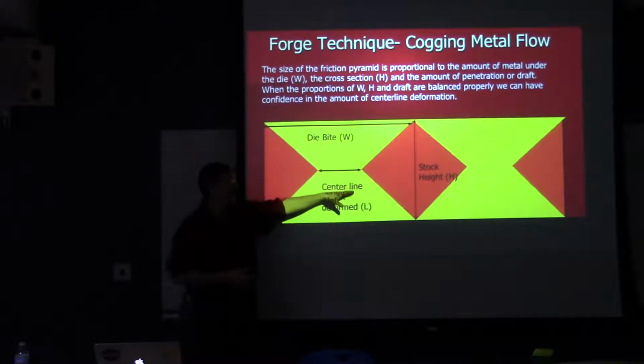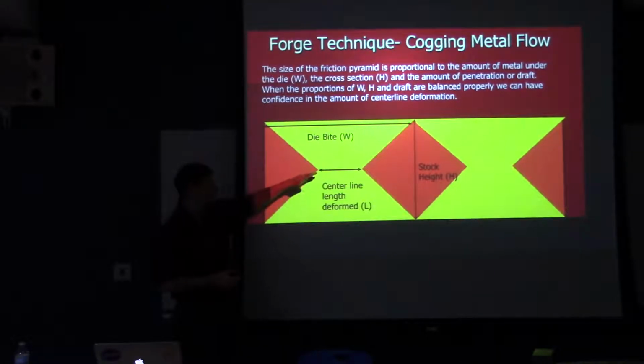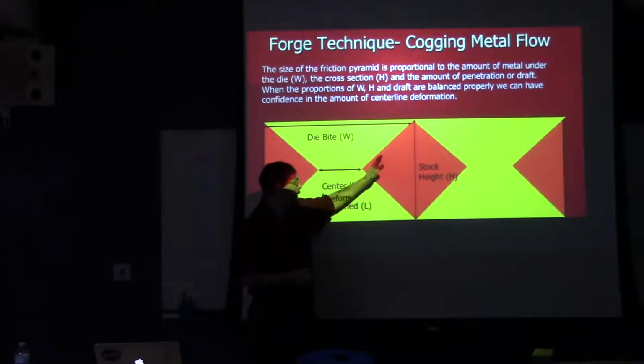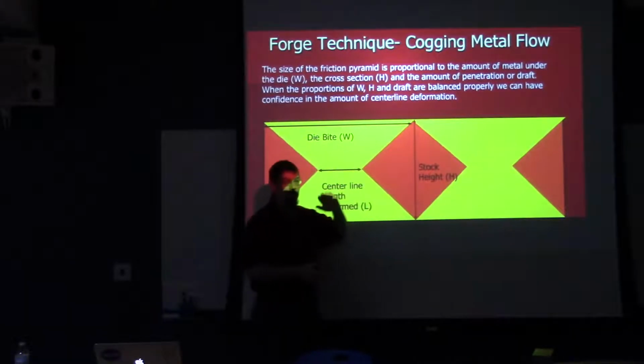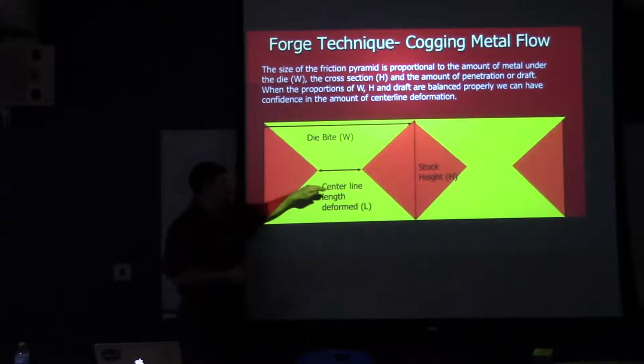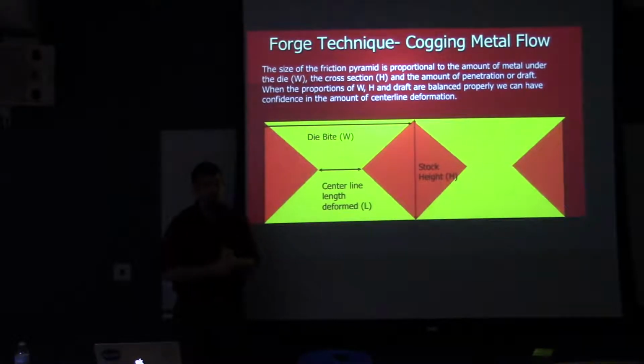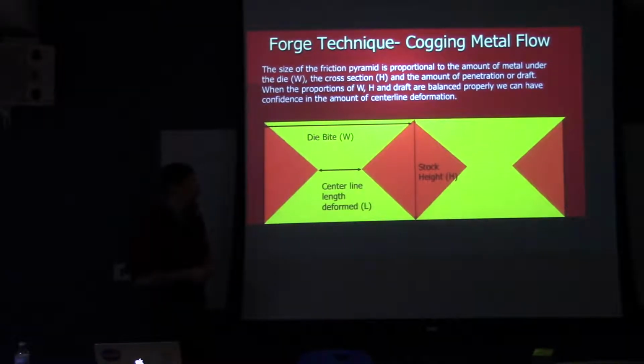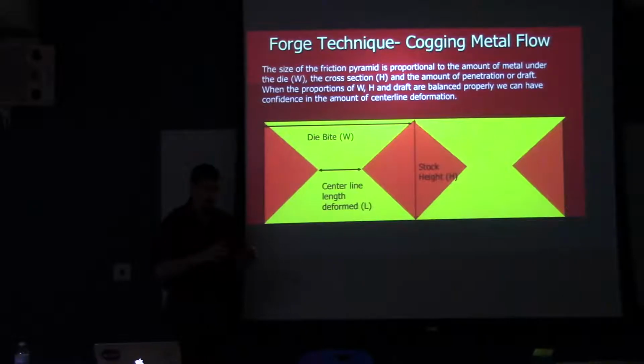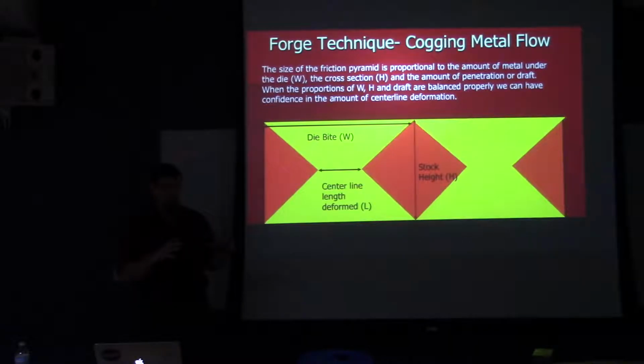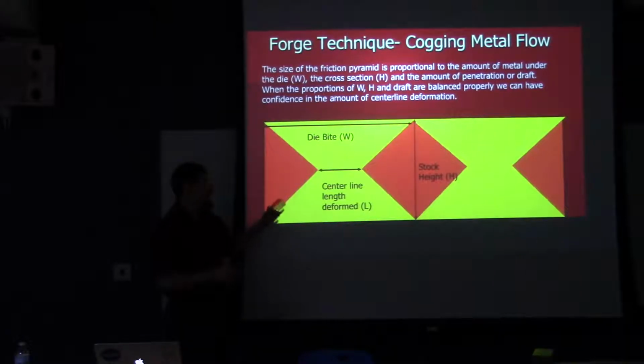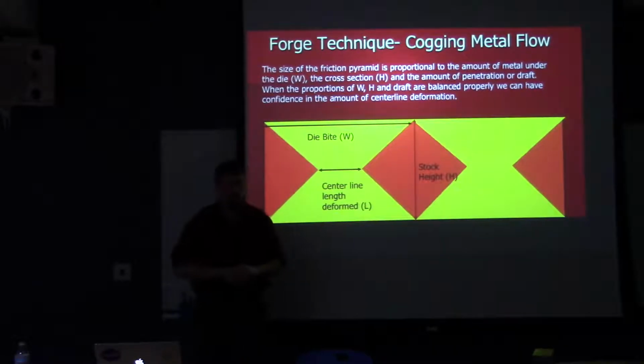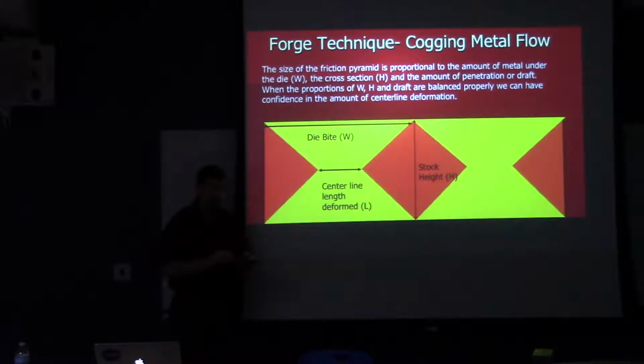So that tells us that if we made 3 perfect passes that were properly overlapped and staggered down the length with these criteria, we should be able to close up all of the porosity along the length of the ingot. From that, we also can calculate that we would need a change in cross-section area. So if I had a 10-inch square, that would be 100 square inches. I'd need to reduce that to a third, so 33 square inches. If I do that, I should be able to close up all of the porosity. That's kind of our ideal.